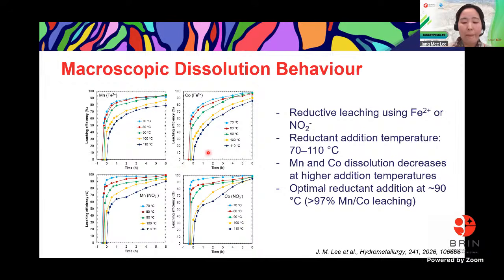As you can see here, the reaction proceeded for 6 hours at 110 Celsius. But what we made different in each condition is the temperature at which the reductant is added. So we added the reductant and ore at the same temperature, but at different temperatures between the tests. We added the reductant and ore from 70 to 110 Celsius, and then increased the temperature to 110 and maintained it for 6 hours. That is the reaction condition.